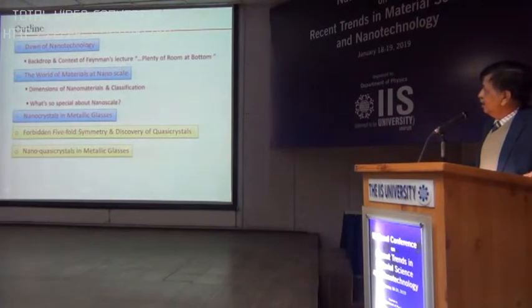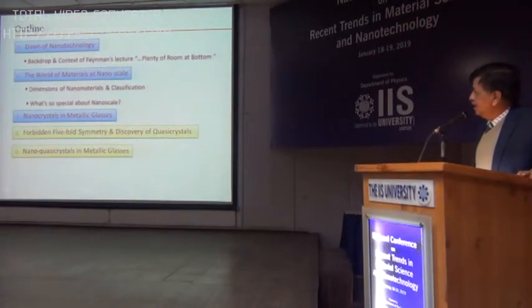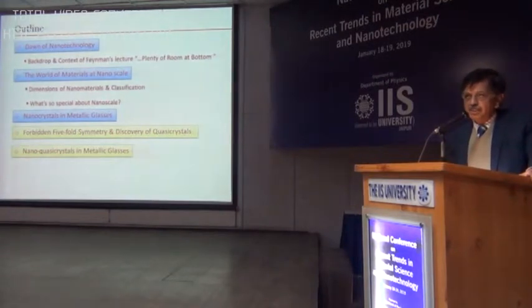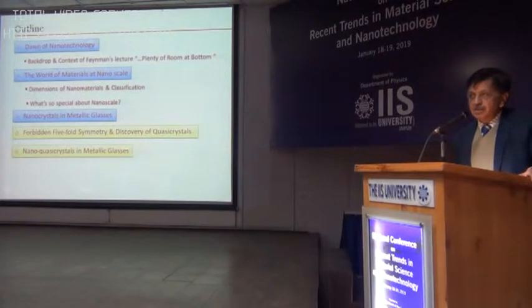What Feynman said, that there is plenty of room at the bottom, and then I will talk about nanomaterials, and then quasi-crystals, nano-quasi-crystals, and then their applications, or nanomaterials in metallic glasses. My field has been metallic glasses, which are amorphous in nature, by controlled crystallization. Because they are amorphous materials, but if you do controlled crystallization of these metallic glasses, you can have nanophase, or you may not have pure single phase nano, but you can have a mixed phase, which will be basically a kind of composite of nanocrystalline material and crystalline material, or nanocrystalline material and amorphous phase.